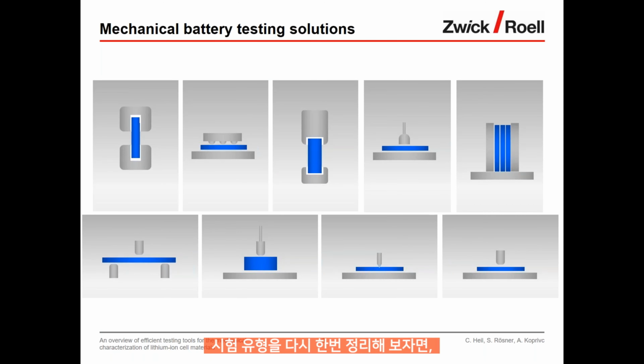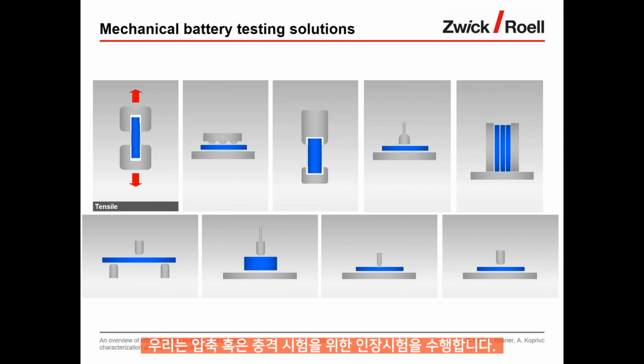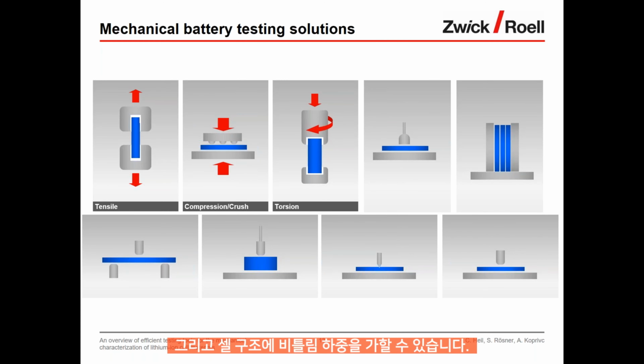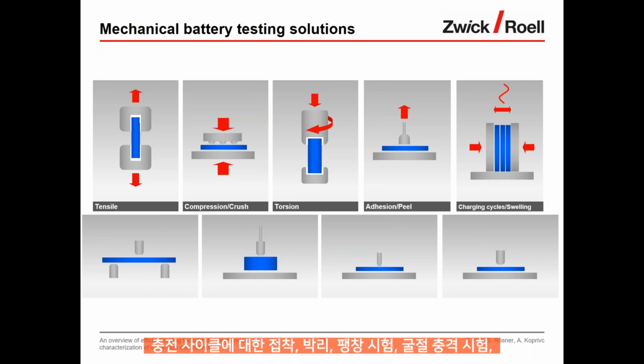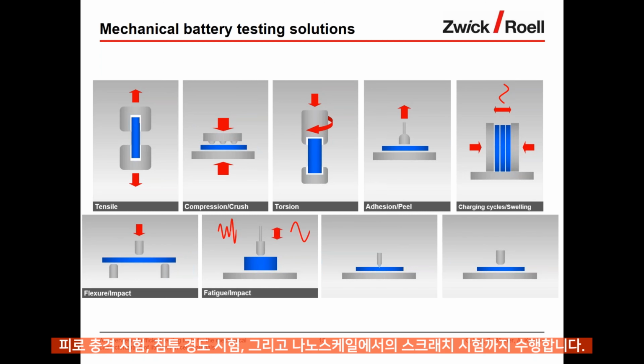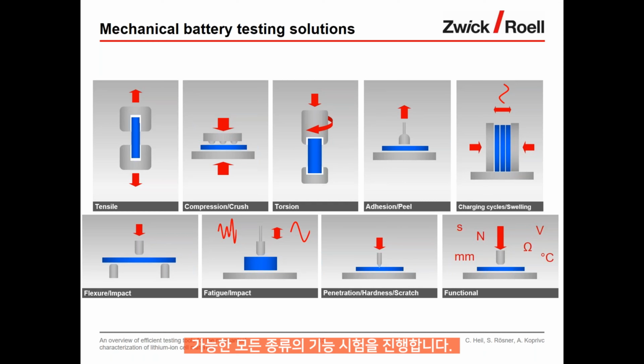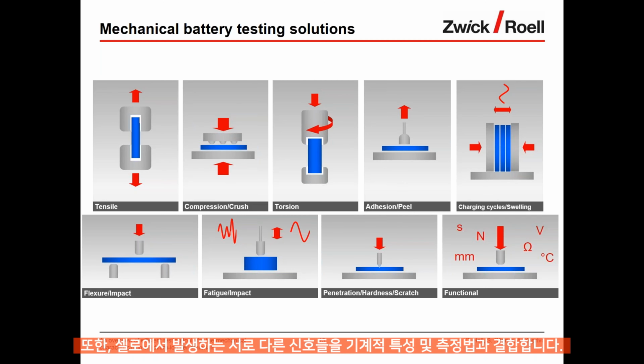Okay, to sum up the types of tests again, we're doing tensile tests, performing compression or crush tests. We can apply a torsional loading on the cell structures. We do adhesion and peel testing. We do swelling tests during charging cycles, flexural impact testing, fatigue and impact testing, nail penetration, hardness testing, scratch testing on a nanoscale as well. And we do all kinds of functional testing where we combine different signals from the cell with the mechanical properties measurements.